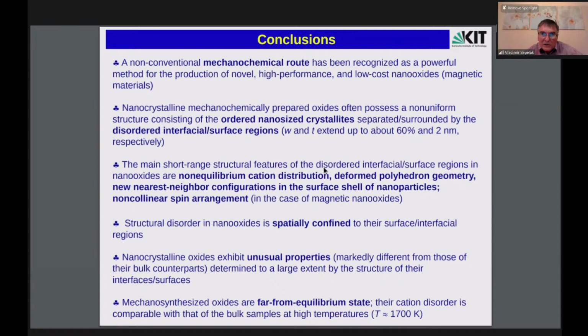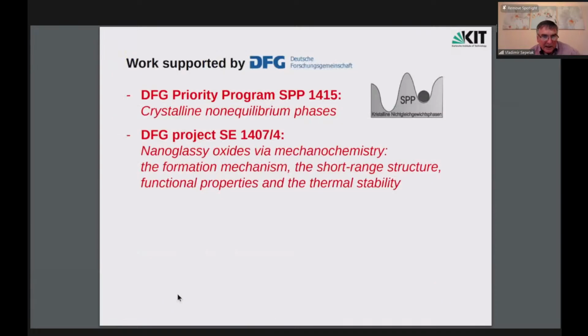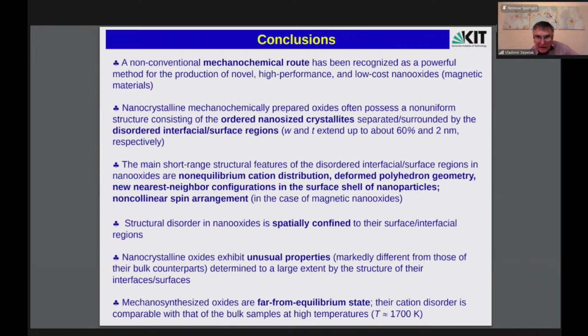And the main short-range structural features of this disordered surface region in nano-oxides are non-equilibrium cation distribution and deformed polyhedron geometry. I did not show you probably the appearance of new nearest neighbor configurations in the surface shell of nanoparticles, but I also showed you the appearance of non-collinear spin arrangement in the case of magnetic nano-oxides. Structural disorder in nano-oxides prepared by mechanochemistry is spatially confined to their surface interfacial region, and nanocrystalline oxides exhibit unusual properties markedly different from those of their bulk counterparts, determined to a large extent by the structure of the interfaces and surfaces. And mechanosynthesized oxides are far from equilibrium state, and their cation disorder is comparable to that of bulk samples at high temperature. I showed you one example with the temperature 1700 K.